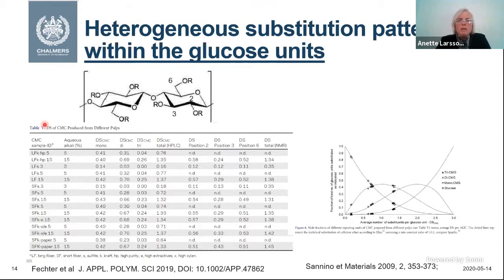So here I will give an example from Professor Thomas Heinze's group in Germany, where Katrin Fletcher and he showed for CMC that if you have a low degree of substitution, 0.35 here, then you can see that the number of substituents on the 2, 3, and 6 position is about the same. But when you increase the number of substituents, then you can see that you will have about the same number of substituents on the 2 and 6 positions, but much less on the 3 position. So this position is less substituted.